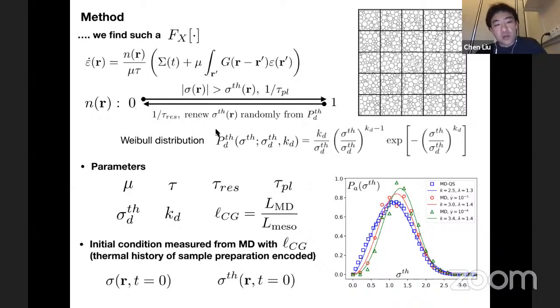And once it returns to zero, a new random local threshold is drawn from a distribution. We choose this distribution to be a Weibull distribution because in the literature it's already measured, and also in our work, that the local thresholds can be reasonably described by a Weibull distribution. And then at the end we have to choose a mesh size of the elastoplastic model that corresponds to the actual size of our molecular dynamics system. And that gives the coarse-graining length scale.